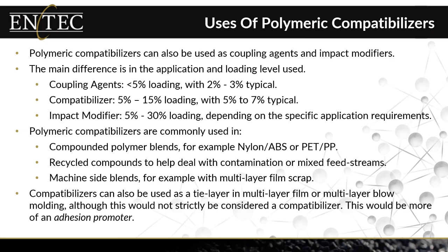And if we increase the loading level of these even further, we can use them as impact modifiers. And so we usually use a range of about 5 to 30% for impact modification. And you'll notice there's some overlap with the compatibilization levels. But as an impact modifier at those very low levels, it provides really practical impact improvement. But if you need to improve notched IZOD impact values, you really need to be at higher loading levels, typically above 15% or so, to really start increasing notched IZOD impact values.